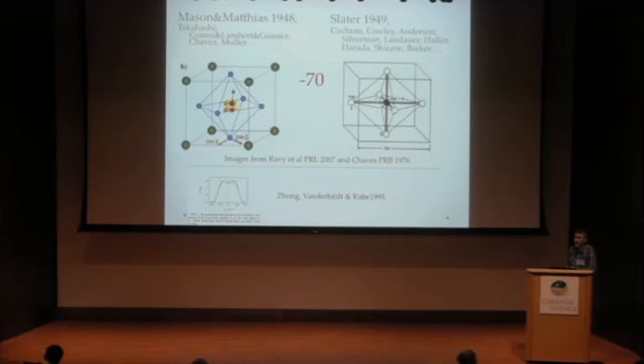So history starts long time ago. So 70 years ago already, it was more or less clear that the titanium goes off-center, as discussed by the previous speaker, in barium titanate. And if you think about the cubic phase, it should be the phase when the symmetry is restored. So on average, the position of the titanium is in the middle of the oxygen octahedra. But if we think not about Landau theory, but about statistical physics, we come easily to understanding that it's useful to think about titanium being somehow off-centered, and maybe there are some specific positions, which is the idea of eight-site disorder of titanium.